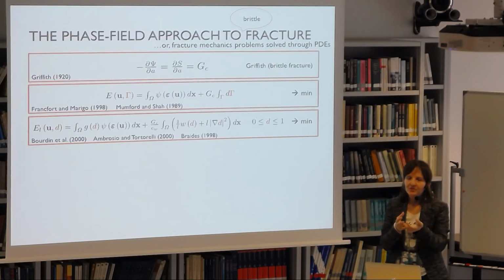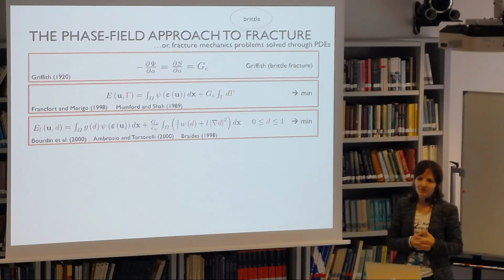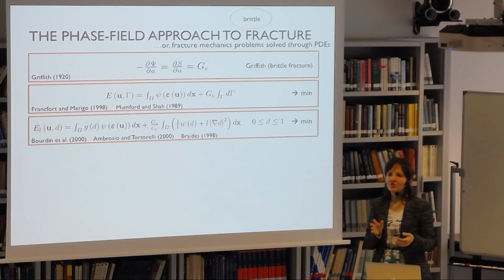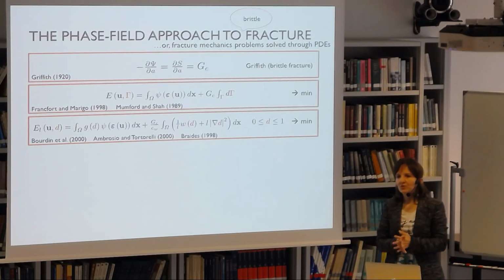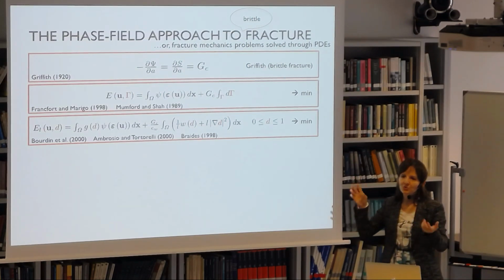What happens sometimes, though, is that I saw a thesis some time ago where they wanted to study concrete, and they computed L based on this critical stress approach, and this L was huge. On the other hand, if you consider that in concrete, fracture doesn't happen in the aggregates but typically in the cement matrix, and you calibrate L based on the cement matrix, which is much more brittle than concrete as a whole, then L was dramatically smaller. Of course, that means you need to resolve aggregates and matrix. But this is my personal view of the problem. If I find out that L is too large, then for me that means the process zone is too large for that specimen, so I can forget about brittle fracture for that.